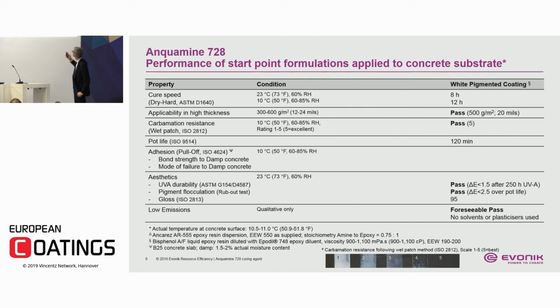The top coat, some basic data. It is less fast, but still in its category in liquid epoxy resin systems. This is one of the fastest waterborne systems you can get, also in the liquid range, comparable to incumbent waterborne systems. At low temperature, you still have about 12 hours. So combine that with the 4 hours on the primer, and you have a system with about, say, 16 to 18 hours. So within your 24 hours, you're done.